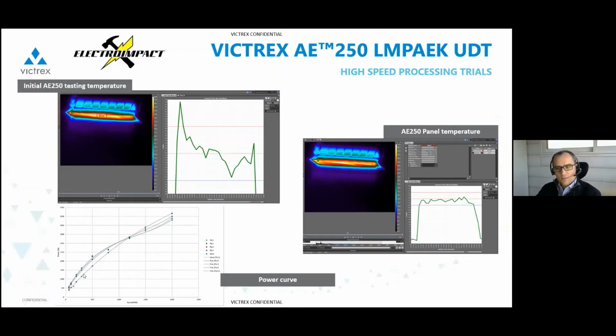That's the power curve. Oops, hold on. Maybe you see my mouse, but that's the curve on the bottom left corner here. So this requires extensive work to really adapt the temperature versus the speed. They also have what they call the VSS, the variable spot size laser heating system. Basically you have one laser for each tow, and that also helps to control and fine tune the temperature for high speed. So this is really part of the settings of the machine before really trying to make the part.